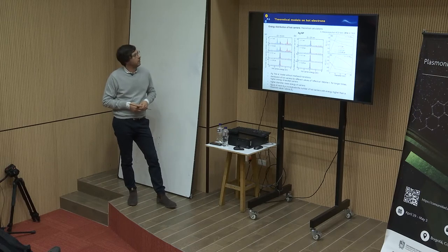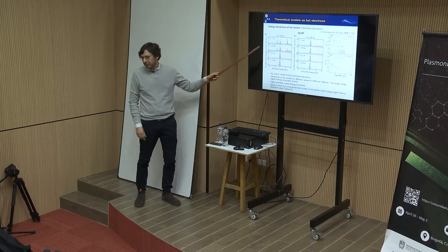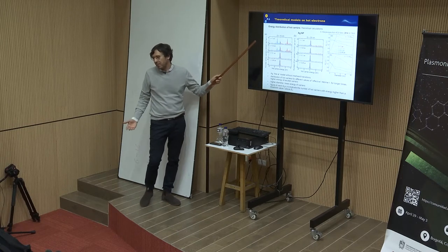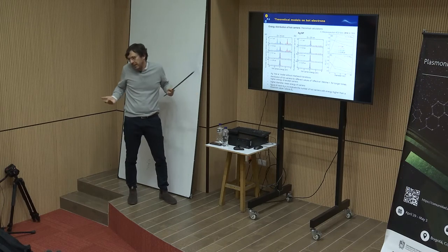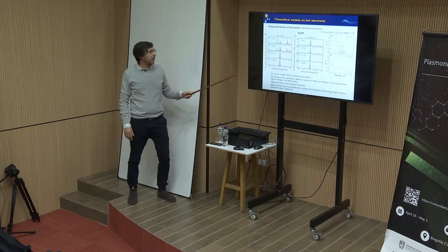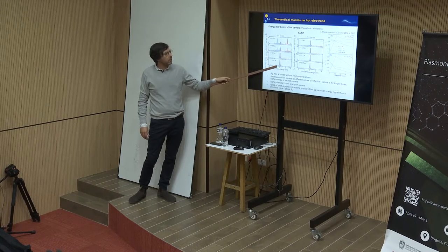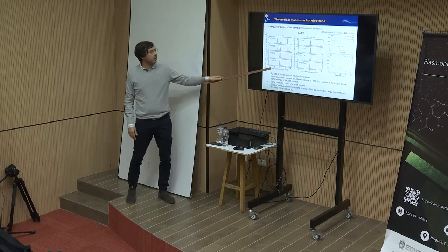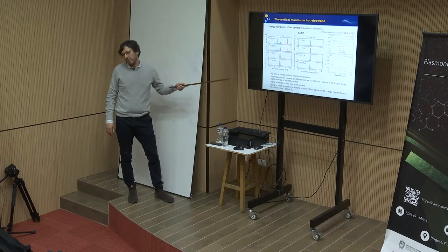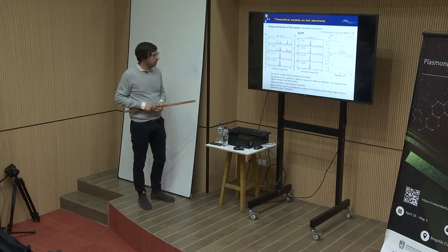Yes. Okay. And what they saw indeed is that if you can prolong the time of the excitation, you can achieve many more hot electrons because you have many more events probably. Otherwise, if you go to more realistic times, you will have many more electrons with an energy close to Drude electrons, and much fewer hot carriers, and this is probably the more realistic situation in plasmonic materials.